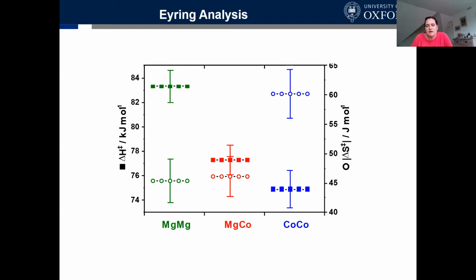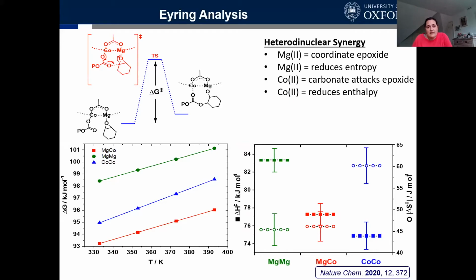So for the open circles, the lowest barrier is now with magnesium-magnesium, and the highest is with cobalt-cobalt. And so if we look at our catalyst that's showing synergy, that's showing better performance than either of its contributing partners, we see that it is, if you like, the best of both worlds, because it combines the low enthalpy in the transition state that cobalt appears to deliver with the low entropy for the transition state that magnesium appears to deliver. And this is a really quite interesting finding, because although synergy is very commonly claimed in catalysis, it's very rarely rationalized. And we appear to have a rationale that relies on a particular metal delivering a particular function in the transition state. So as I've said, magnesium reduces the entropy and plays the role of coordinating the epoxide. So perhaps it pre-orders the transition state. Cobalt reduces the enthalpy, which is completely consistent with it providing the carbonate nucleophile that attacks the epoxide. And as I've said, this is our hypothesis that explains how synergy functions in these types of catalysts.